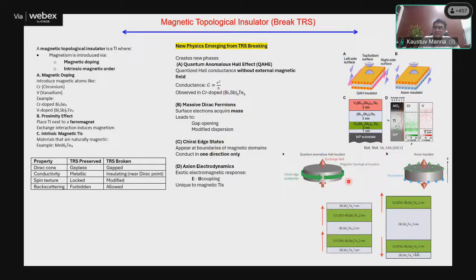Second, if you independently polarize in the opposite direction, so one is up spin and another is down spin, the up spin breaks the down spin polarization, whereas the down spin breaks the up spin polarization. The consequence is that both the edge states are gone, or let's say gapped, from the system. That is what is shown here. The top and bottom surfaces of the topological insulator are already gapped, but with this proximity effect we are now manipulating the edge states. Either one of the edge states is protected, as in the quantum anomalous Hall effect, or both of the edge states can be gapped.